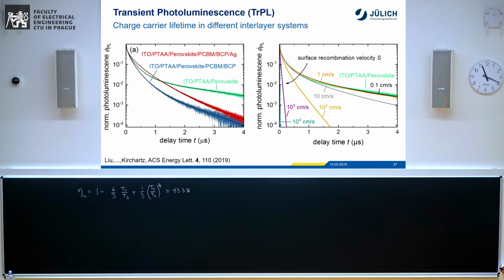And honestly, I think these transients are very complicated and difficult to really interpret because there are so many things happening at the same time. So we only bothered to then look in detail at this, where we have 1 interface and the perovskite, that looked like it could be done. And what we did was, essentially we thought we have 2 key reasons why the luminescence is going down. Either it's the bulk or it's this 1 interface that we're having. Yeah? Because we know that perovskite towards nitrogen, which is the environment in which we did the experiment, has very low recombination velocities.